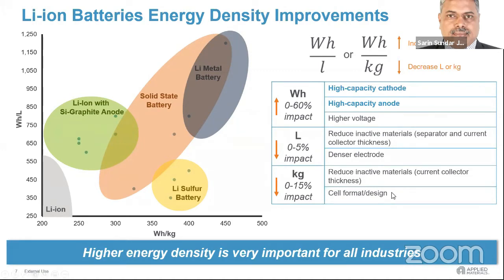Just to quickly show what we are working on, we were working on high energy density. When we say high energy density, it can be watt-hour per kg or watt-hour per liter. Watt-hour per liter is typically volumetric efficiency for things that you carry in your pocket, like mobile phones. Lithium cobalt oxide is typically around 400 to 500 watt-hour per liter. But still, the lithium cobalt battery takes about 40% of your phone volume. It's a large real estate driver for watt-hour per liter. But for all other applications, typically it is watt-hour per kg.